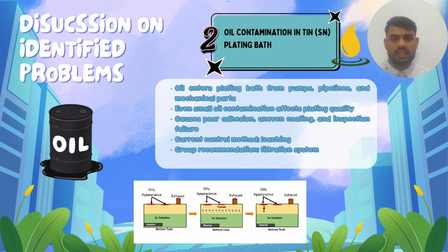When the oil is present, it creates a barrier between the lead frame surface and the plating solution, resulting in poor tin adhesion, uneven coating, and surface defects. These defects often cause rejection during outgoing QC, which is quality control, especially for the SSOP and DSOP packages.